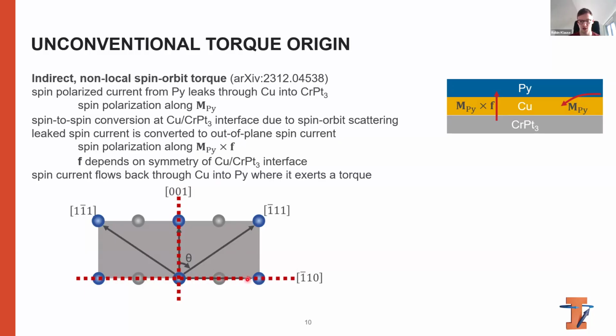If we apply current along these two directions, the vector F is such that the spin polarization only has a conventional direction and no unconventional one. But if we apply current not parallel to these mirror planes, like at negative 54.7 and positive 54.7 degrees, then F is such that the spin polarization can take on a component that is along the current direction.